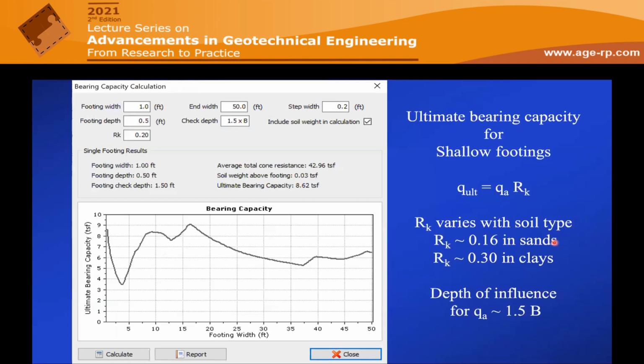And then for design, for footings, people often like to estimate what the ultimate bearing capacity of a shallow footing is. And rather than apply bearing capacity theory and parameters, it's been observed that there's a direct link between the average cone resistance underneath the footing and the ultimate bearing capacity with this correction factor. And the correction factor is around 0.16 for sands and up around 0.3 for clays. And so the software allows you to select the average Rk value, and it defaults to a value of 0.2. So if you have mixed sands and clays, it goes halfway between the two. And the zone of influence is 1.5 times the width of the footing.